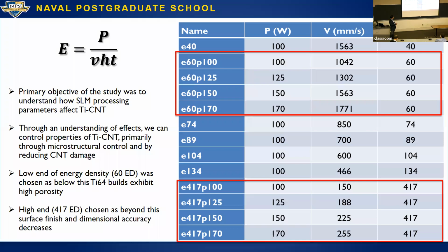But aside from potential damage or reactivity with the CNTs, you actually lose resolution at this high energy. When you have such a dynamic melt pool, you're inputting so much energy into the melt pool that it becomes very turbulent, very unstable, and you're not able to get very nice, precise surfaces. And my very last slide of this topic will have some images of parts we printed. But you do lose resolution, which practically is a problem.